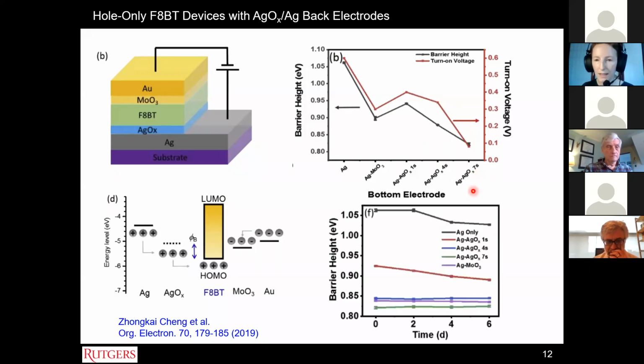Zhongkai also looked at the stability of these devices, and you can see that compared to silver only, the barrier height changes as a function of time more so than compared to the intentionally oxidized surfaces. So they stay very constant over time.